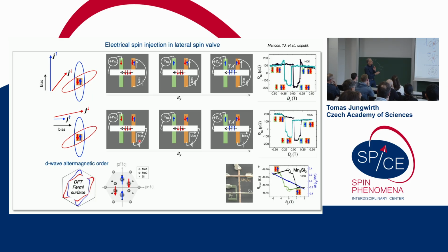So in the normal non-local spin valve, where you have the ferromagnetic injector, and we can also talk about injection from non-magnetic platinum, where there's also interesting phenomenology, what happens is that you have the injection electrode, and then you have the copper channel. And most of the injection is actually happening when you bias it in the vertical direction through the horizontal interface. The spins are injected into the top copper channel, right? So it's that interface that then matters. Now, you can also imagine, because of how the device looks, that there's a lithography, and then the copper channel goes like this, and then it continues. So you can also have injection from the sidewall here, okay?